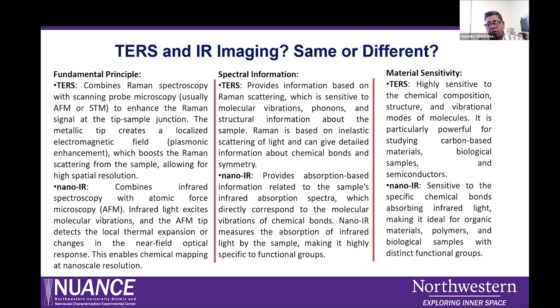So basically, TERS is based on inelastic scattering of the incoming photons. They interact with the surface, and that inelastic scattering gives information about the sample symmetry. It can give the information about the chemical bonds, symmetry, mostly applicable to non-polar molecules. In the case of nanoscale IR spectroscopy, it is based on thermal expansion, because if you're using infrared lasers, you can just direct them toward the sample, and the sample absorbs the laser and it results in the thermal expansion of the material. And that thermal expansion basically changes the mechanical forces between the probe and sample. On the basis of that, you can get the IR spectrum.